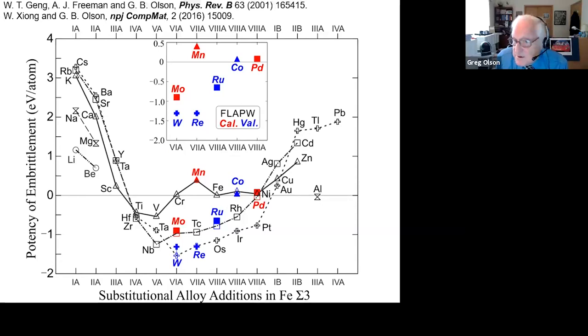By calibrating DFT against a small set of experimental surface thermodynamics data and then projecting across the periodic table, we built essentially a surface thermodynamic genome almost entirely from DFT calculations.